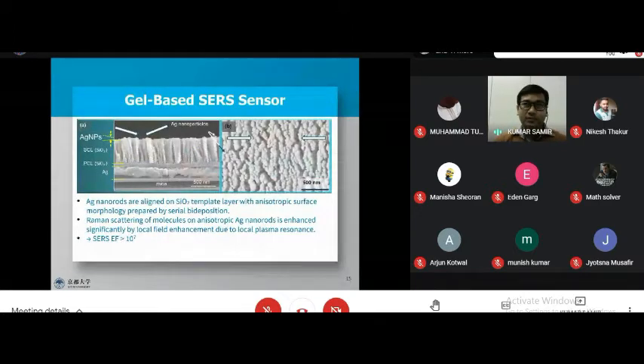For the fabrication of this gel based SERS sensor, first we fabricated the SERS substrate, and that SERS substrate has to have very good enhancement factors. So for that, we fabricated a multi-layer thin film structure of silver, SiO2 and silver nanoparticles, and it has an enhancement factor of more than 10 to the 7. So it's a very good SERS substrate.